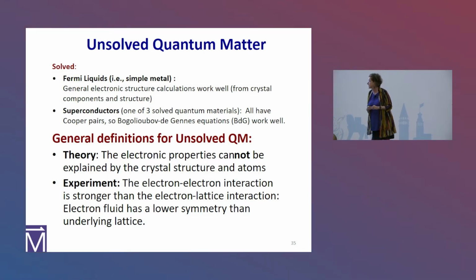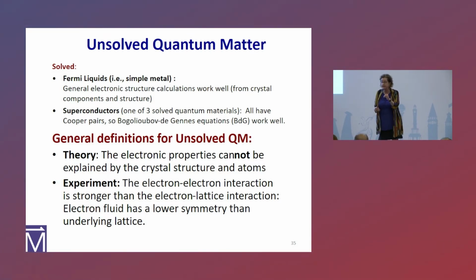So how do we know it's there? Basically, if it's not a Fermi liquid, then the electronic properties cannot be determined by the crystal structure and what's in it, right? Because the electron-electron correlations are so strong. And the second one, which I think of as an experimentalist, is that the electrons break the symmetry of the underlying lattice, right? In the nematic phase, the electrons will pop in like sausages or cigars, depending on what you like, and they're on top of a tetragonal lattice. So the symmetry breaking, and it's just not a solved problem.